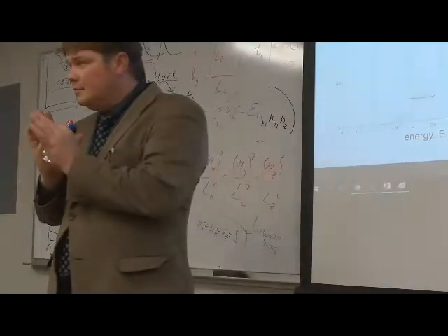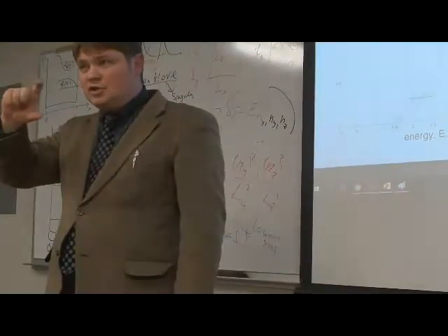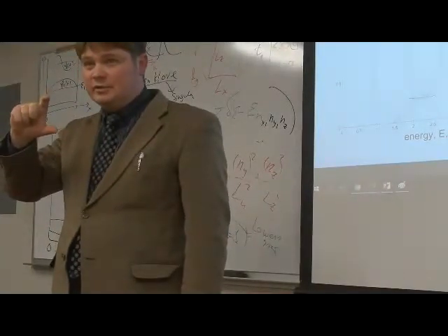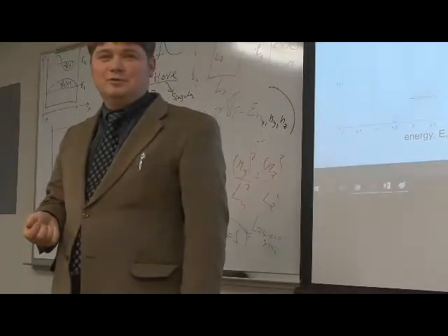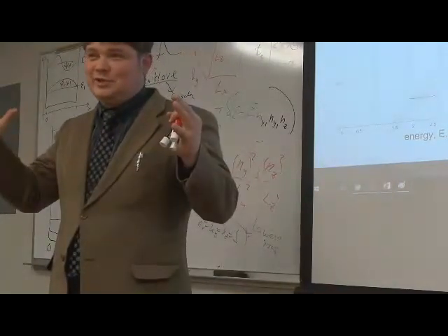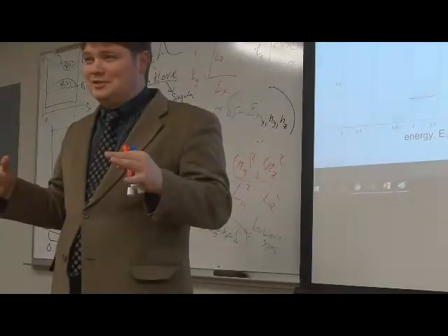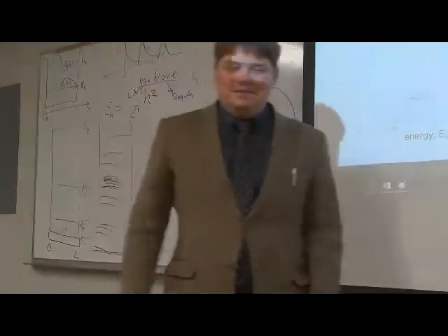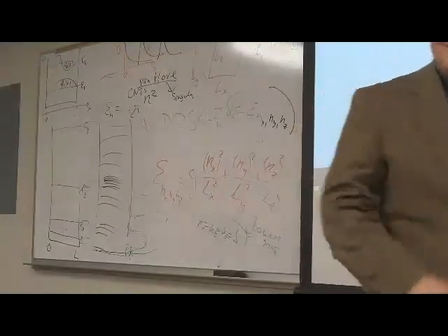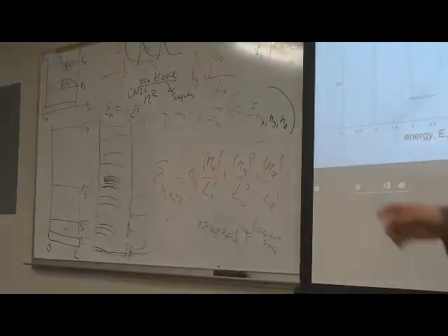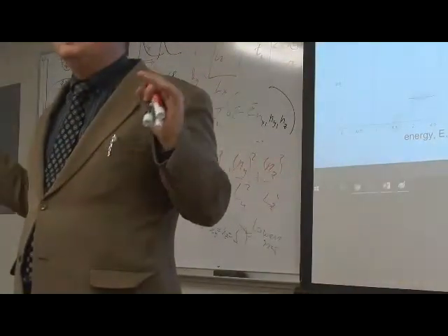By tweaking the size of the box, you can get any transition, any frequency, any color of the material on demand. So it will give me a red quantum dot? Okay, just grow it a little bigger in the synthetic procedure. Most of you are much better synthetic chemists than I am. There are keywords like Ostwald ripening. So please save the image and make a brief comment. How do you interpret it?